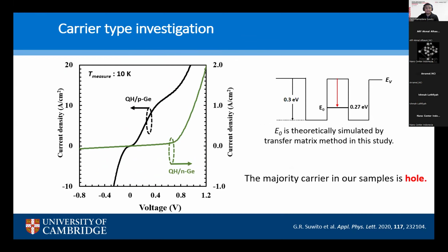Okay, so this is the result for the other sample with N grown on N substrate. And in comparison to those grown on P substrate, the heterostructures grown on N substrate don't show any RTD properties. Instead, they show rectifying properties of a typical PN diode. So this clarifies that holes are the majority carriers in our quantum heterostructures. The possible explanation for this is that the quantum heterostructure is P, so if you grew it on N, you could get a PN heterojunction. And in fact, it agrees with our previous studies that also observed unintentional hole generation using this kind of structure, which is related to the formation of vacancy defects.